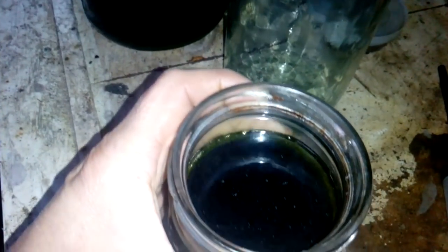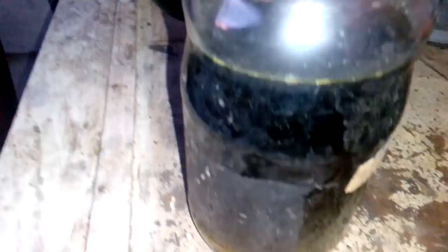Good morning. This is our auric solution from our CPU, and look at this — through the night, look at all that silver chloride on the bottom. If you start to drop the gold with this, it will be very hard because the silver chloride is stopping the gold from dropping. So what I'm gonna do, I will decant slowly into the new jar, drop some gold, and keep that silver chloride behind.